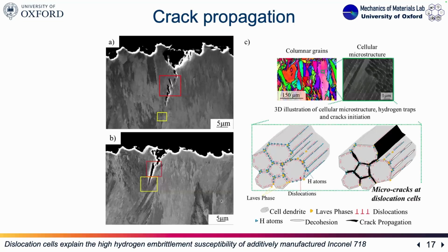An interesting event that we observed with a sample that we have tested, so this is the fracture surface. We looked at it initially in the SEM, and we saw these cracks along the dendrite interface in the AM condition. And then 1 month after, we went again to the SEM, and we saw that these small cracks that had initiated in those interfaces had propagated along the interface. We don't know if it was because of some residual stresses, but we know that hydrogen always provokes these delayed cracking events, right?